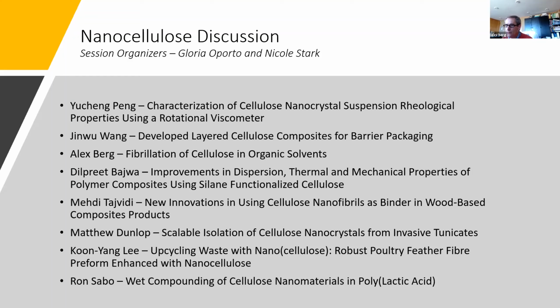About the topic we worked on in our paper: as an introduction, we compared the reinforcing action of acetylated as well as non-acetylated nanocellulose, and we used it in plastic and in wood adhesives. What we observed was a better dispersion on the one side, but also a lower tendency to re-agglomerate between the dispersed nanofibers, and certainly also better mechanical properties of the reinforced material.